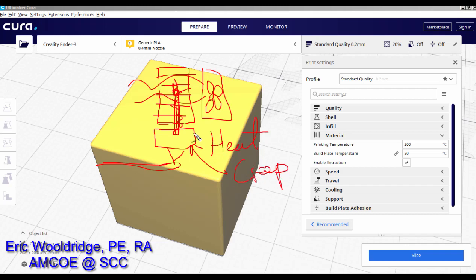And you don't like heat creep because it causes you to have clogs, it makes the motor jam up here, and all kinds of problems. So sometimes if the material doesn't call for it, raising the temperature too high is going to create a clog issue, and so you want to watch that just as well. Now you go too low and then you don't have a good layer-to-layer bond, it doesn't flow well, and you have to watch out.